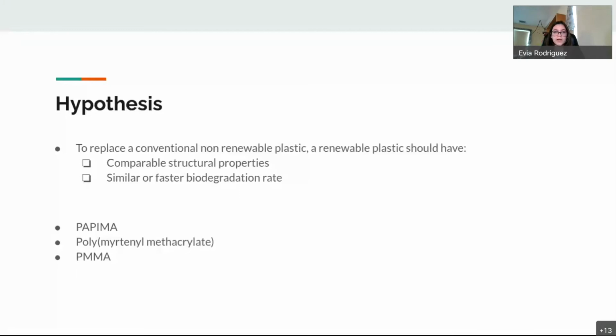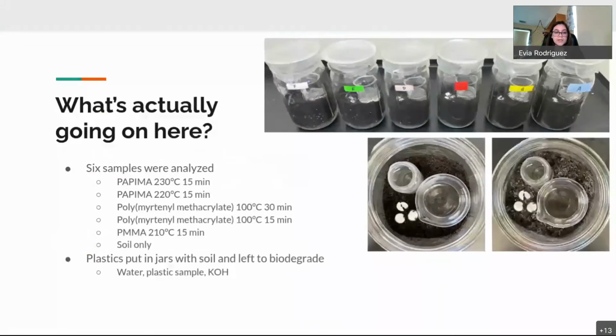So what's actually going on in my experiment? I analyzed 6 samples of plastic, 2 samples of PAPIMA, 2 samples of poly(myrtenyl methacrylate), and 1 sample of acrylic, and then my control sample was soil only and no plastics. So the temperature and time you see next to each plastic sample, when these plastics were synthesized, because they use supercritical carbon dioxide, a powder was created, not the actual film. So in order to create that film, the plastics needed to be melt pressed, and this required them being heated up to a certain temperature, which is listed next to each plastic sample, and then pressed for a certain amount of time.